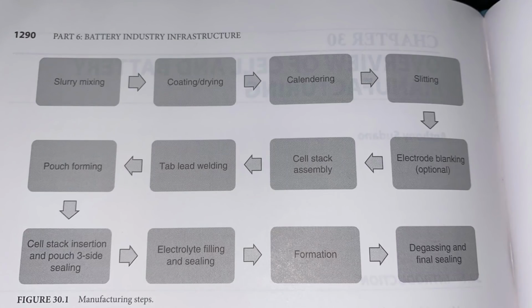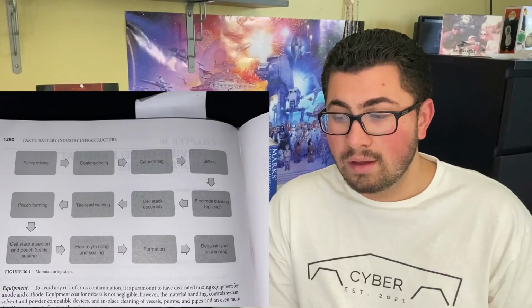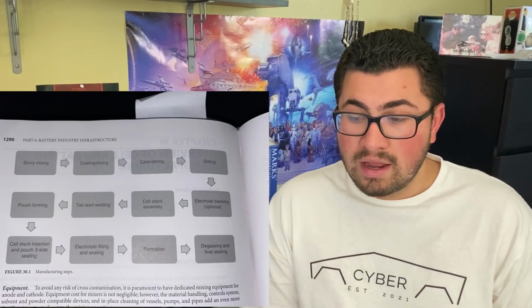Well, generally they're made two ways. They're made by coating, which is the same way that you make a battery, and the other version is extrusion. Coating is the traditional process that batteries are made from, and that involves taking an active material in carbon and combining it with binders, like a polymer, and mixing it with a liquid additive. The additive reacts with the binder and dissolves it, but the additive overall is not good for the performance of the cell. So they try to bake it off and get rid of it, and when they bake it off, the binder re-dries, and that's how you get the battery electrode component as a whole. It's that dried portion of it. That's why you put it in an oven.